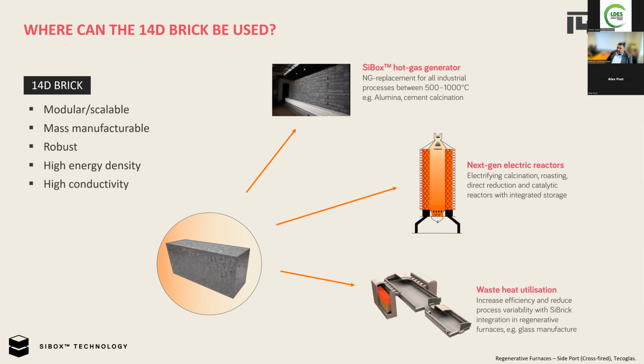You can also use these bricks directly in waste heat utilization. For some of the industries like glass, where you have regenerative furnaces, and there is fuel port switching every few minutes or so, one of the key constraints for these furnaces is to maintain a constant temperature profile inside the furnace, and having a phase change material in there at a very high temperature would give you that opportunity to minimize those fluctuations.